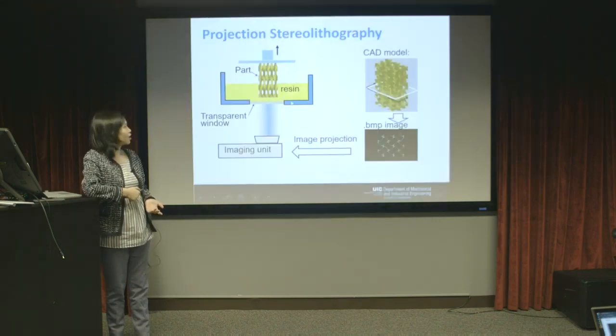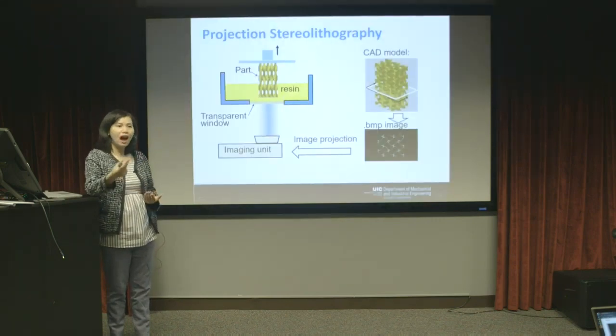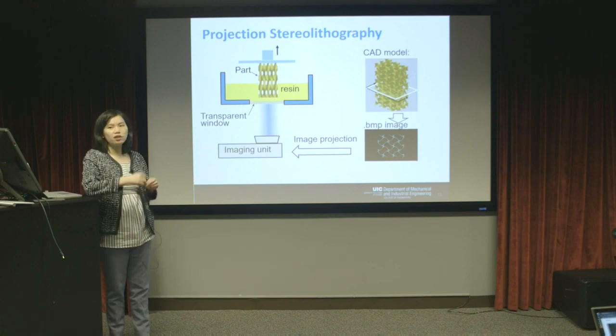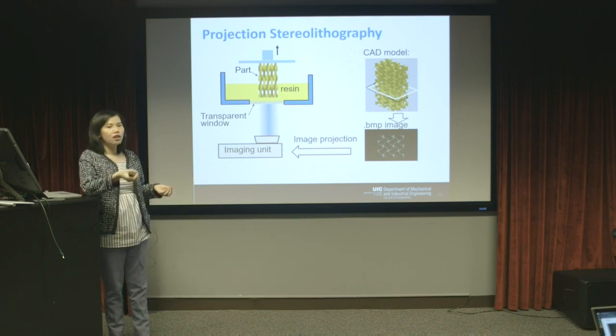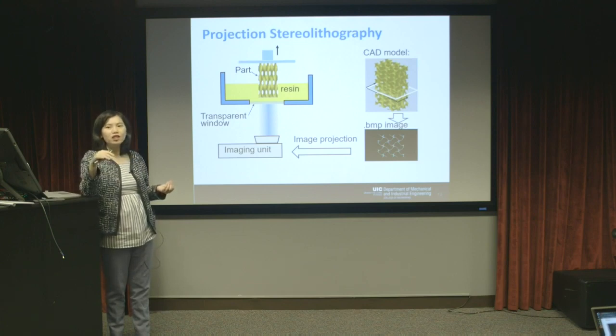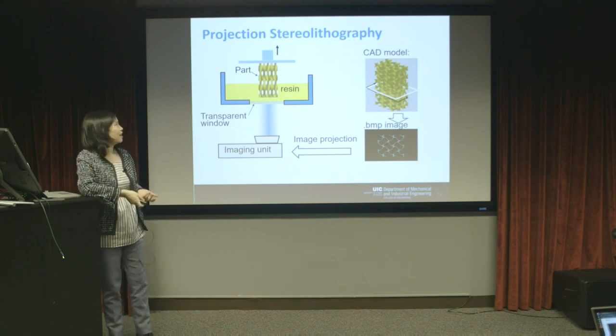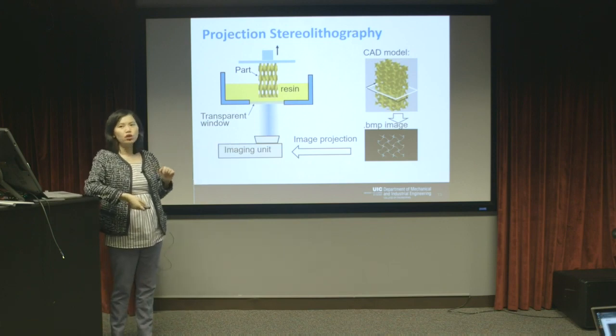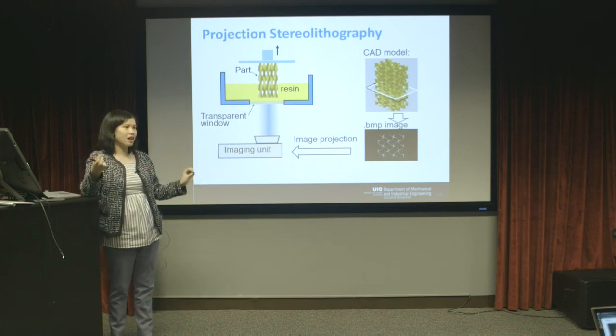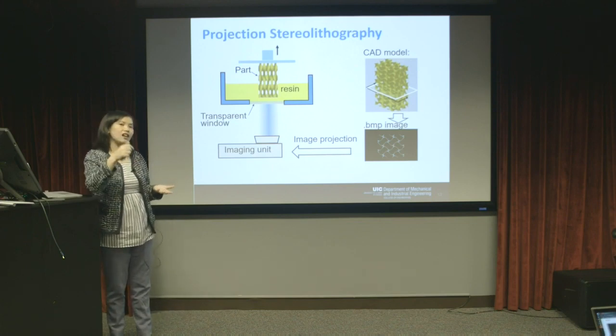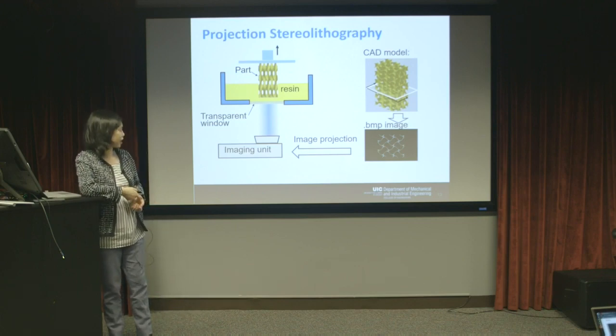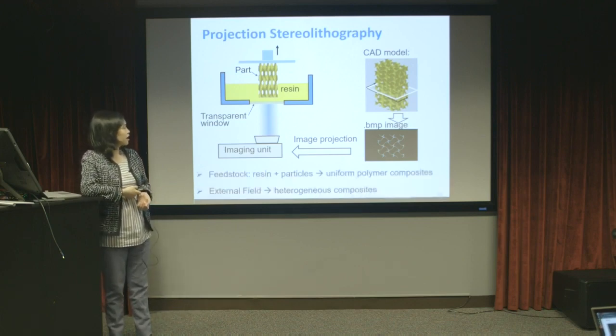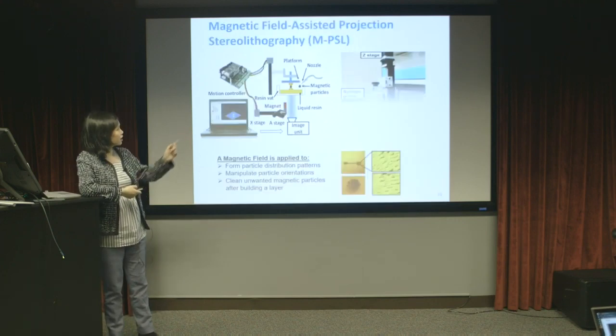And when the liquid resin is exposed to the light, to the white light, because the light energy is so strong, the photosensitive liquid resin gets solidified through a photopolymerization reaction. Then in this way, you can use the image to define the geometry of that layer and solidify a layer with that geometry. And then you can build those layers one by one and stack them to make a 3D object.